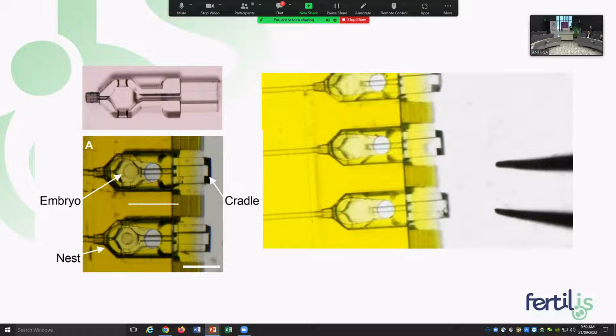So how is Fertilis harnessing this technology in microIVF? We've essentially built a microfluidic system for the embryo. In the first instance, we've created a cradle for the embryo. Printed on the Nano One, this allows for easy retrieval of the embryo, rather than using a pipette, which can cause stress. It's similar to a baby capsule that allows you to move from the car to the stroller or to inside without actually disturbing the baby. The cradle is 300 microns wide, 300 microns high, and less than 1 millimetre long.